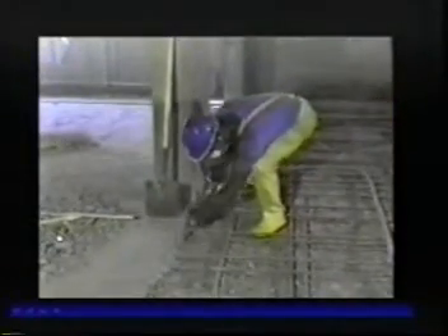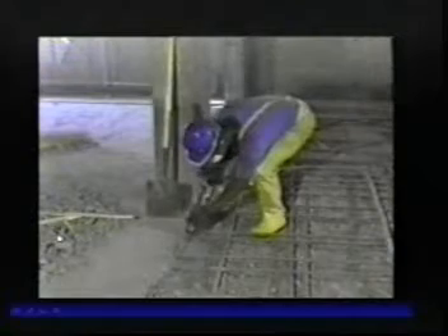The edges of repairs for all these techniques, all three of these techniques, require square shoulders, which is a combination of using cut-off saws like this, either hand or floor-mounted saws, making a saw cut generally less than half an inch so you don't cut the existing reinforcing steel. So a combination of saw cutting and hand chipping squares up the shoulders of these repairs so that we end up with a uniform thickness throughout these repair techniques.